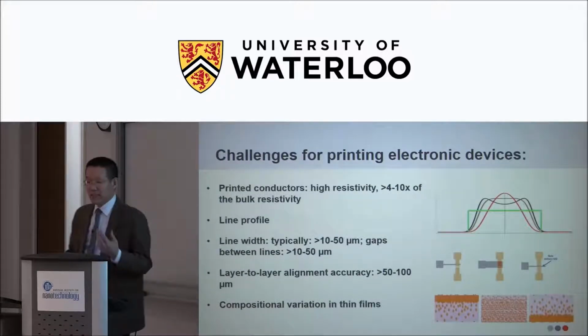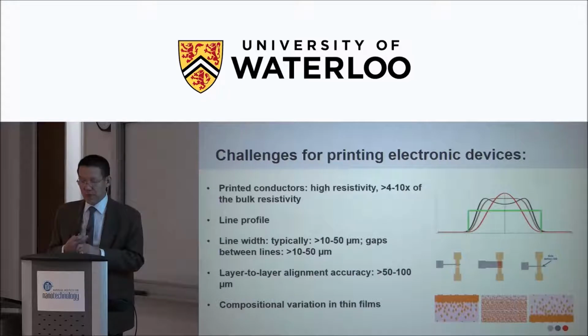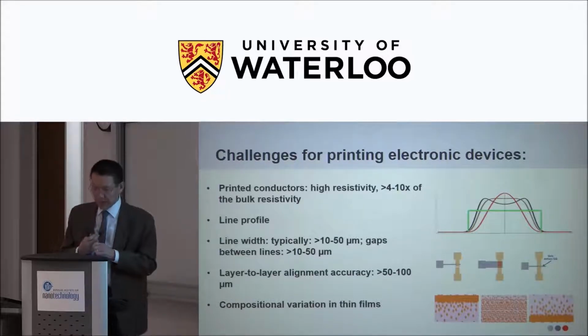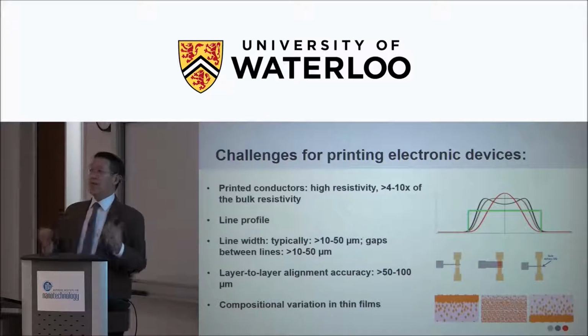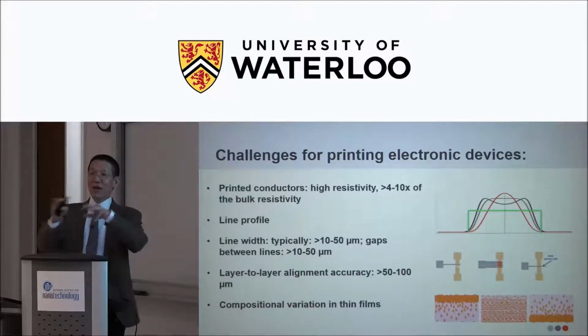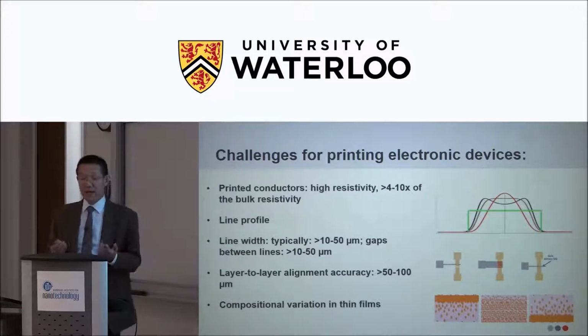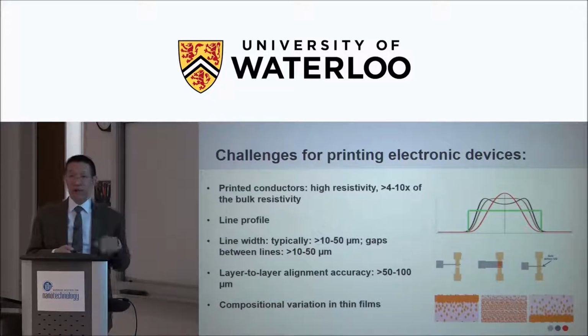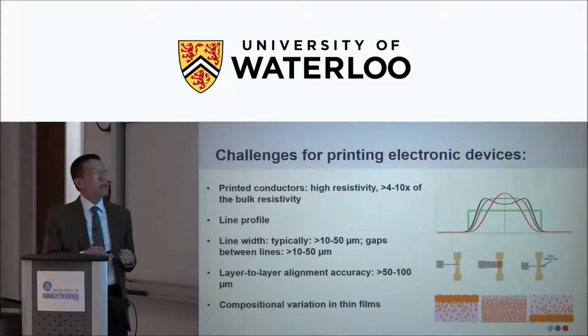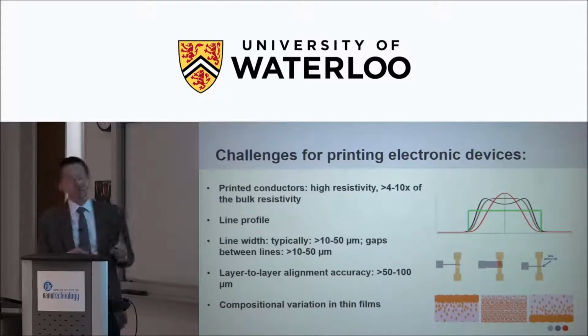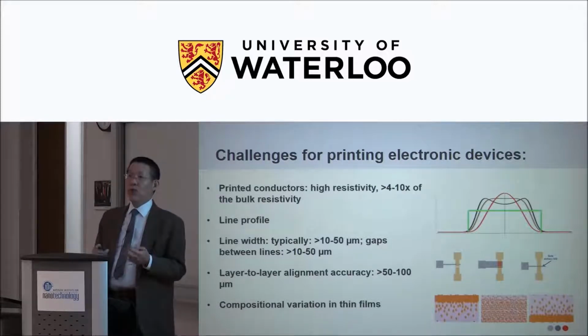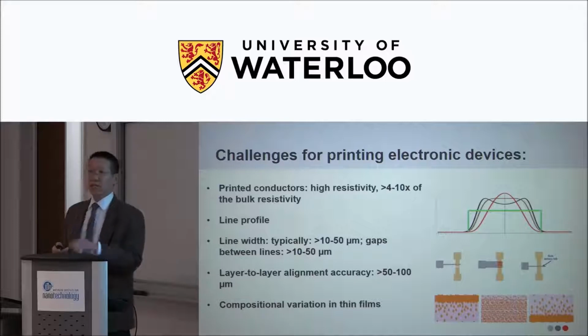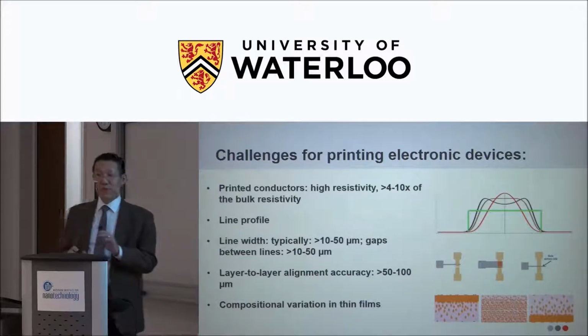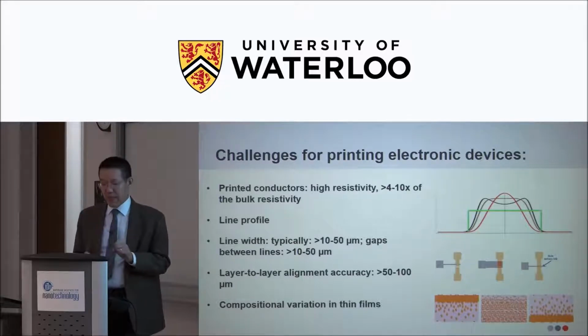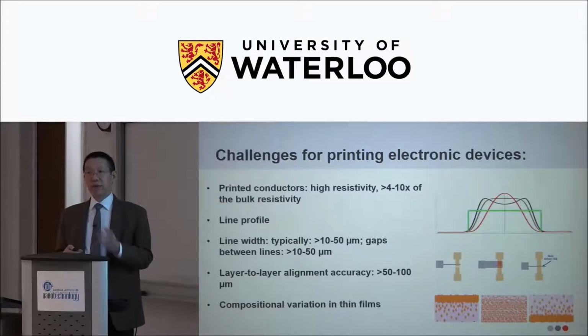So at the beginning, as I discussed before, people were really hyped about printable electronics. We thought we could do a lot of things with it, almost parallel with silicon devices. By the end, it's almost not possible. We have to find the right application for printed electronics, right? So first of all, when you print metals, for example, up to now, no metal ink can provide the same conductivity as bulk metal. That's almost impossible. And they are always more resistive than the bulk metal.